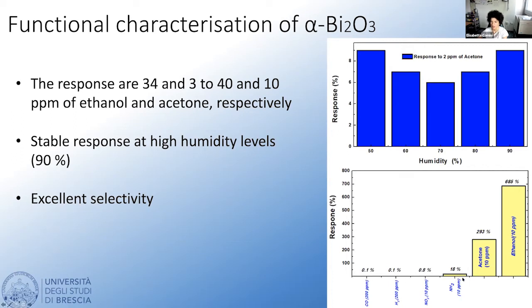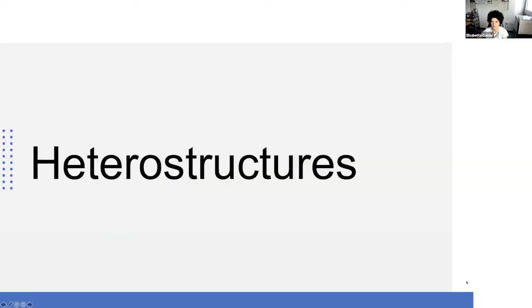And we can see here that the highest response is towards ethanol and acetone, while the other compounds have much lower responses. So the problem is that, as you have seen, we have no perfect selectivity over different compounds.